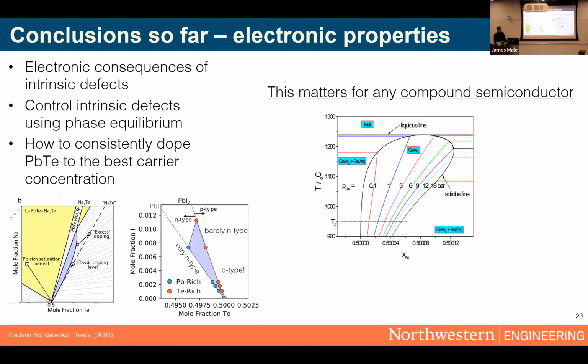Essentially, any binary compound has a phase width due to the defects. And you can even see that in this classic gallium arsenide system, where there's a similar sort of phase width that should give you different doping properties depending on if you're gallium or arsenic rich.